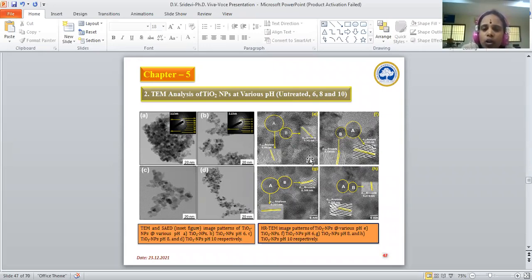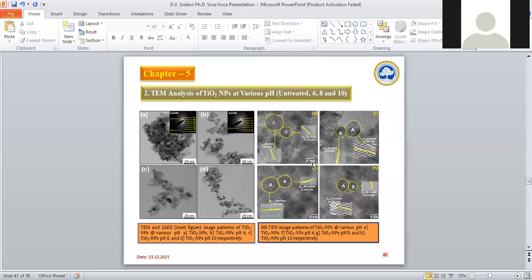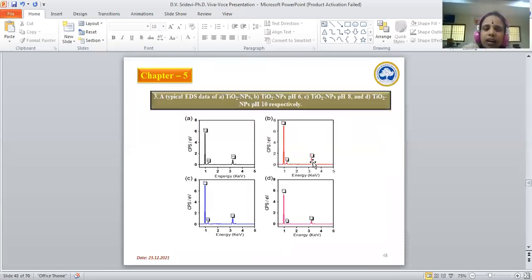The d-spacing values for anatase were found to be 0.354 nanometer, 0.343 nanometer, 0.321 nanometer, and 0.285 nanometer, and 0.306 and 0.274 nanometer for the brookite phase, which is in good agreement with the powder XRD data. This slide shows the TEM EDAX analysis of the synthesized compounds, which confirms the presence of titanium and oxygen.